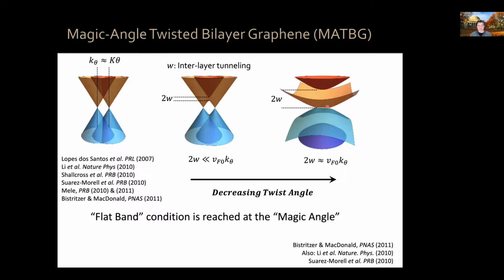And this flat band condition is reached at the magic angle, which happens to be 1.1 degrees for graphene on top of graphene. Okay, so there was interesting theoretical and experimental work about a decade ago about the single particle physics, essentially, of how this process happens and this magic angle, which was coined by Bistritzer and MacDonald.